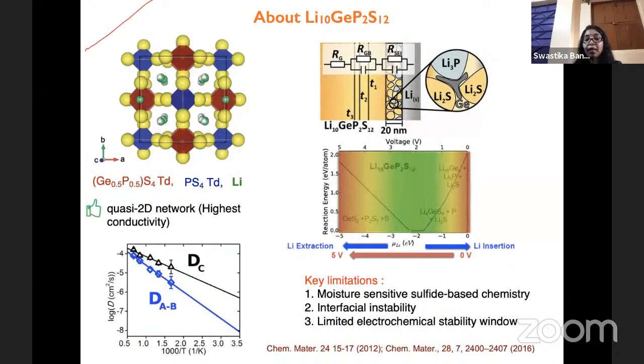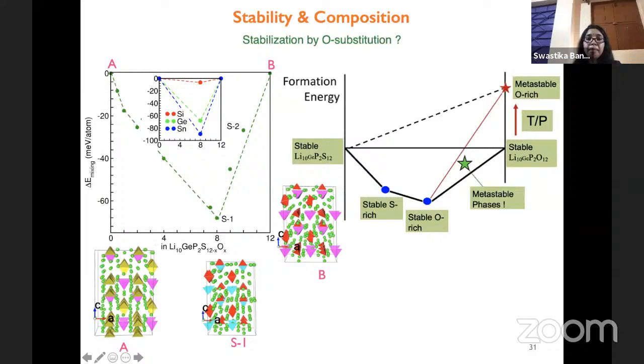And again, I'm just showing the LGPS framework because I worked on this LGPS framework, and this is the summary so far which I have mentioned. So the key limitations are again moisture sensitivity, interfacial instability, and the electrochemical stability window. So what we did is we mixed the oxygen into the framework of the LGPS, and we find that if we keep on increasing the oxygen concentration, at certain intermediate concentration, we have the minimum energy or the stabilization.